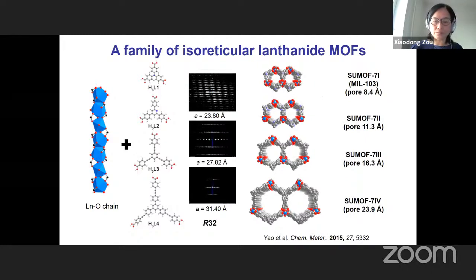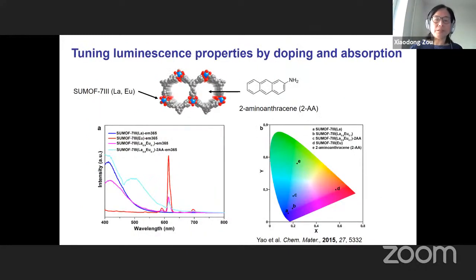As you see here, they all look like a triangle, but different sizes. So when you have larger and larger linkers, the pores become larger and larger, which means you can tune the pores. And because this is lanthanide, you can use different elements, and you can get different properties. For example, you can tune the luminescence property just by doping different lanthanide elements. Here you can dope, and then you can make use of the pores to insert different gas molecules to change the luminescence properties. So by these two different things, you can really change the color of the absorption of the MOF in a different wavelength range.